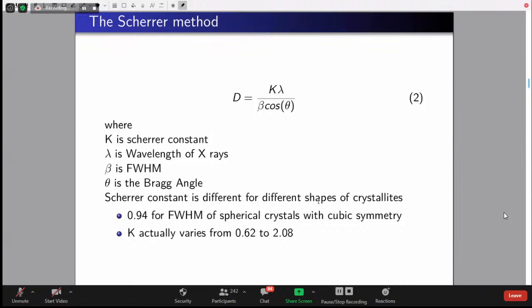Or else, if you don't like this 0.94, you can just use 1. Mostly that is a heavy approximation. It's not going to change things much. Instead of 0.94, you can use 1. But when we are using tetragonal, triclinic, monoclinic, very low symmetry ones, it is better not to use the Scherrer formula for crystallite size. It overestimates the crystallite size. Then you will be disappointed.